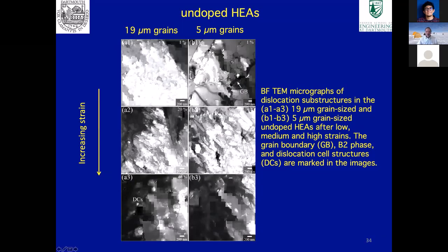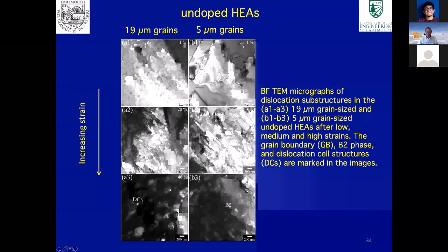Again, we looked at the dislocation structures in this material. In the undoped high-entropy alloy, we just got these sort of wavy dislocations, leading to dislocation cells, and you can also see the B2 particles here, where there's quite a lot of dislocations forming around those.